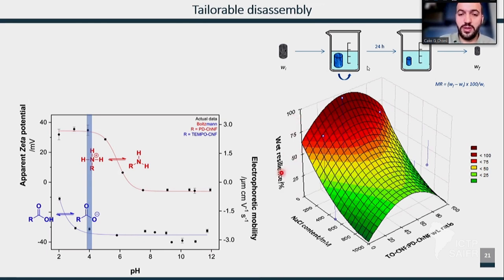So we did, this is a wet resilience. What is this? It's a very simple experiment. You have water, you have your foam, you put it there, stirring for 24 hours, and you see what lasts and what was dispersed, right? So I'm playing here with decomplexation, separating the complex species. So let's see the wet resilience. The higher the wet resilience, the stronger is the complexation. When it's stronger, as expected, when I have a proper ratio between cationic and anionic species, right?